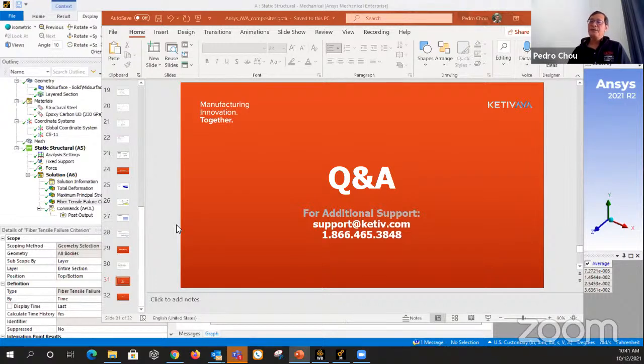You have the A, B, and D matrices, which would be the stiffness in extension, bending, and coupling, and then use all those terms to assemble the element stiffness matrix. So basically, the information that you use for each layer will calculate the stiffness for each layer, and Ansys will combine the stiffness for every layer to give you a single element stiffness matrix.